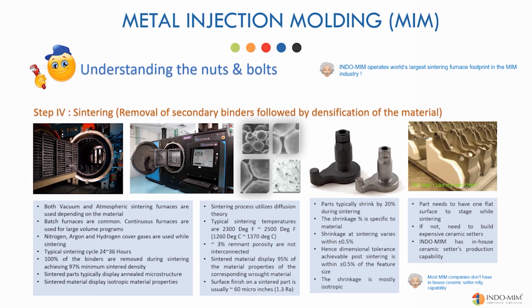The first 12 hours of the cycle are spent on removing the secondary binders through thermal debinding process. After all the binders are removed, the furnace temperature is ramped up rapidly to the soaking temperature where the metal particles diffuse with each other. At the end of the sintering process, all the particle boundaries are replaced by grain boundaries. At this stage, the component shrinks by a specific percentage, squeezing out all the empty space left behind by the binders. The shrinkage is mostly isotropic, meaning the component shrinks at the same percentage in all the directions.